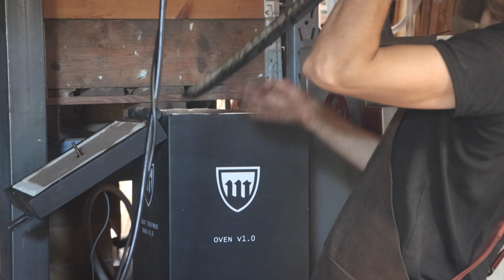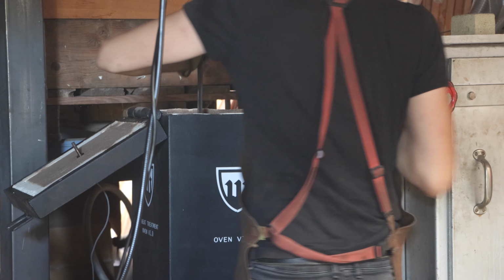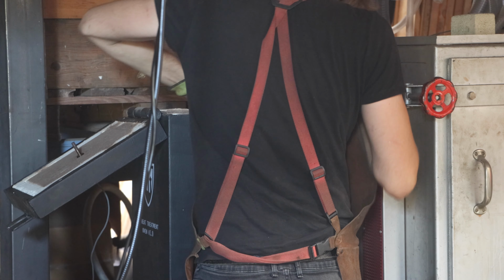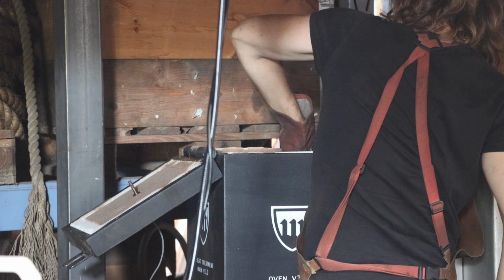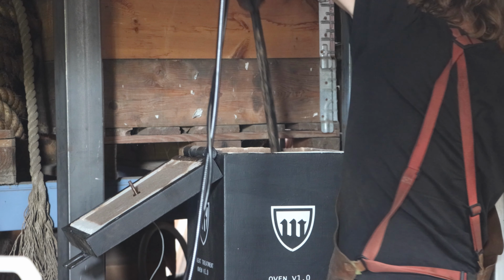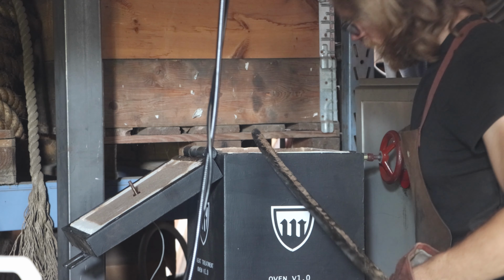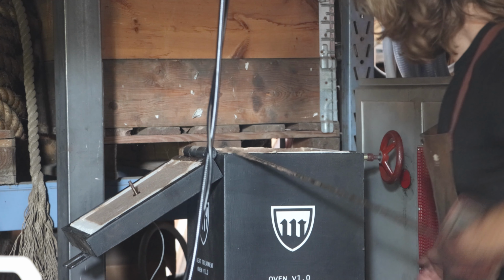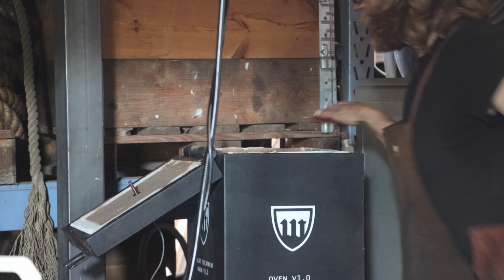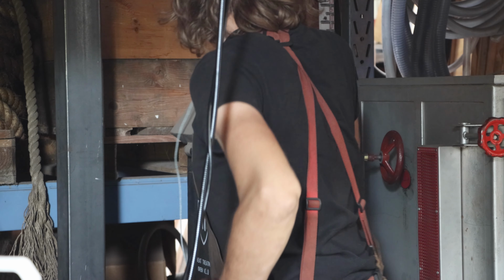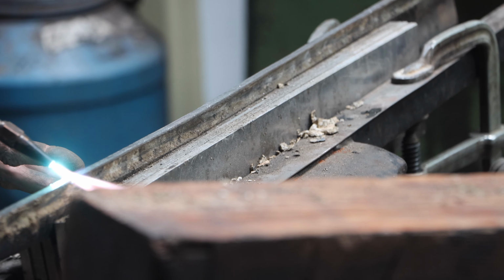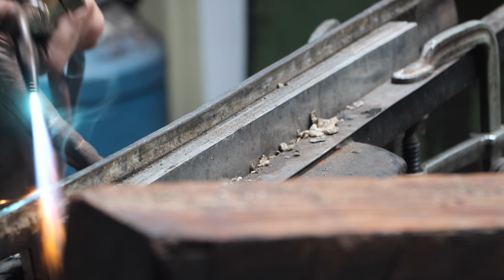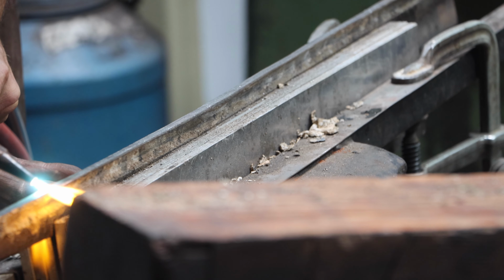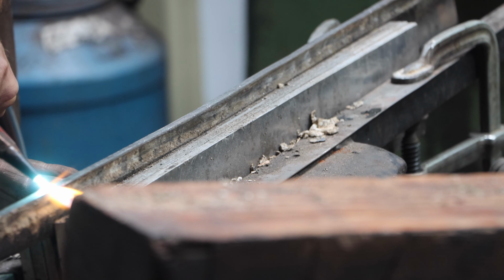After hardening, the blade is placed in an oven to temper it, loosening the steel crystal structure a bit, releasing uncomfortably trapped carbon molecules. This process helps a lot in making the blade tougher, but some hardness is lost. After the temper, a second temper is done, further relaxing the blade. Corrections to the blade can be made now, but only when it's hot.